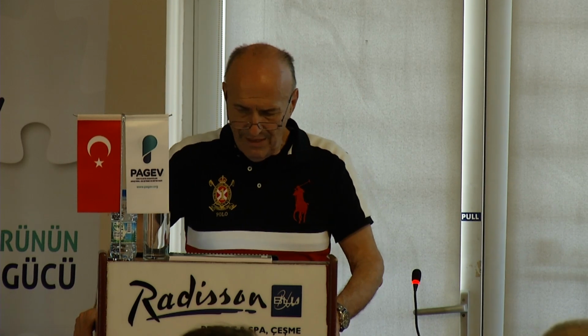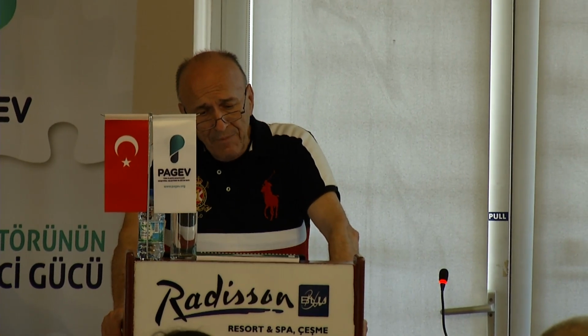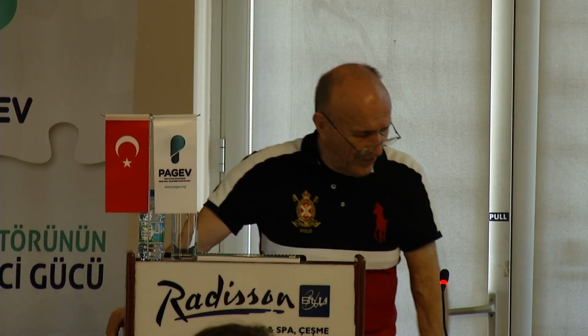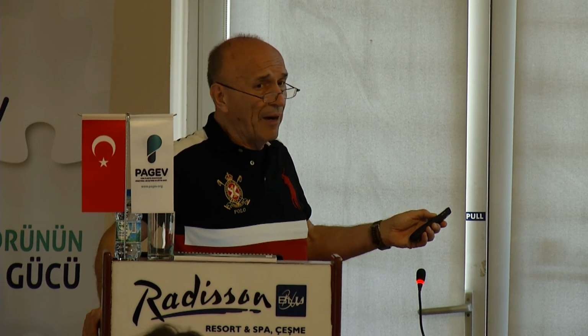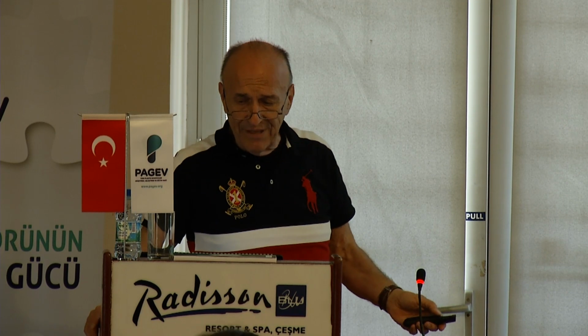My guess in that case was that it was probably purchased. They had paid for it, you know, when the supplier gave them the resin, it was already there. But you might have generation of gels or some form of degraded materials right in the screw. Now, we frequently recommend that this kind of screw with a sharp corner like this should not be used. It is better to have a rather wide angle right here. And what happens in those cases, on both sides of the screw flight, you have the generation of gels.